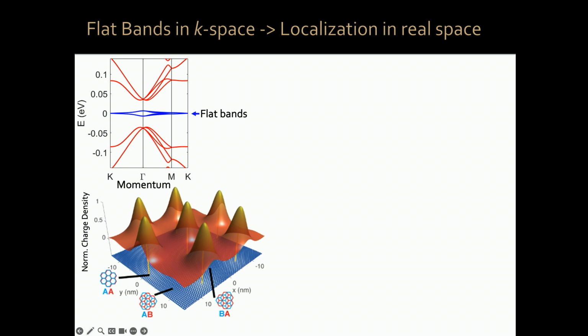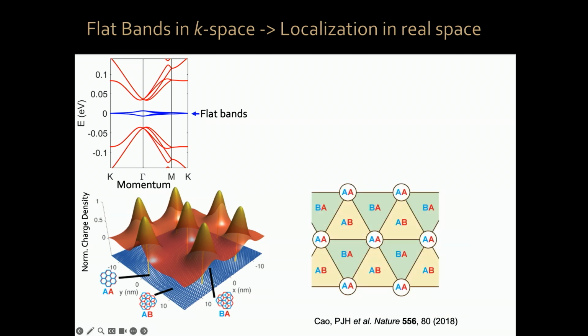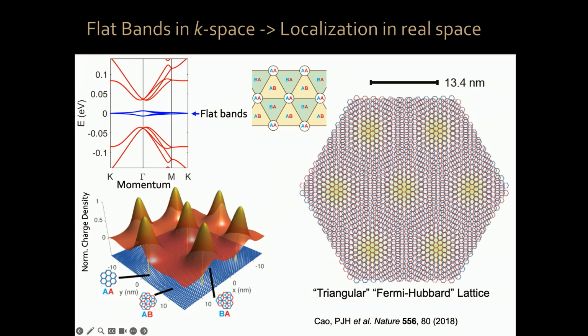And in those regions, the electrons do not like to be. So schematically, magic angle twisted bilayer graphene looks like this. You have these regions of AA stacking where the electrons like to be, separated by regions of AB and BA stacking where the electrons do not like to be. In a slightly more realistic schematic, you have these regions of AA stacking shaded in yellow and separated by about 13 nanometers where the electrons like to be, and then separated by these regions where the electrons do not like to be.